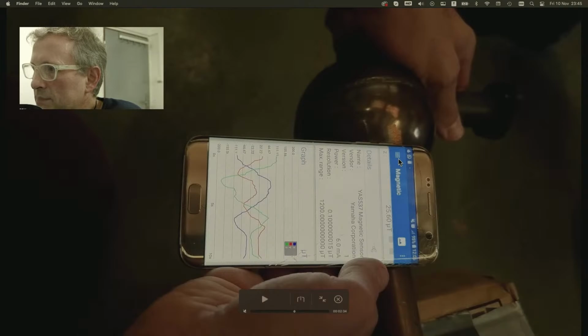It's pretty explainable. But where the interesting thing comes in for replicators is to define if there's any magnetization before you do anything to it. Particularly, do not get a magnet near it. Because to remove that magnetism, you will have to do two things. One, you will have to raise it to 600 to 750 degrees C, let's say, something around that ballpark, to go through the Curie point of the stainless steel to mess up those magnetic domains.